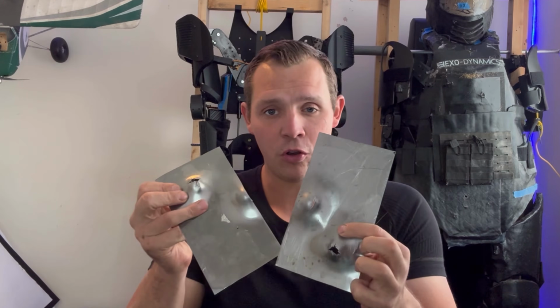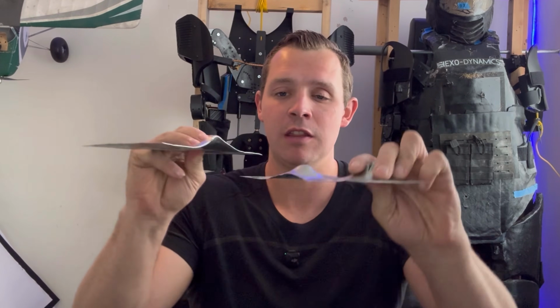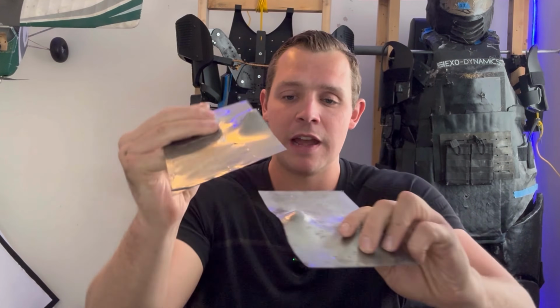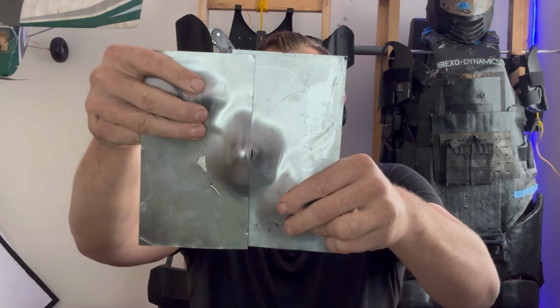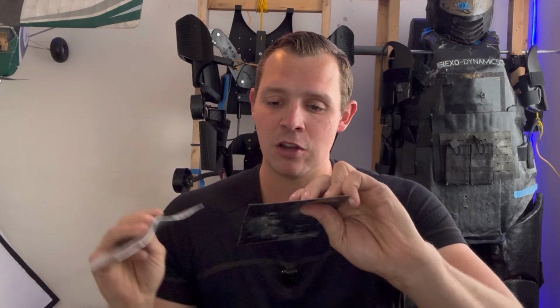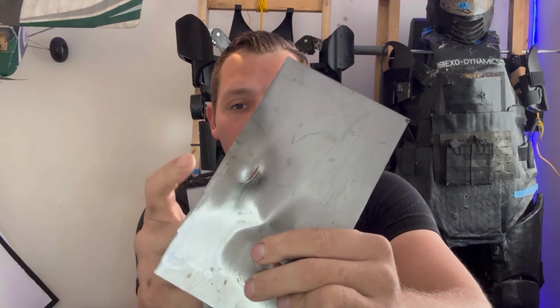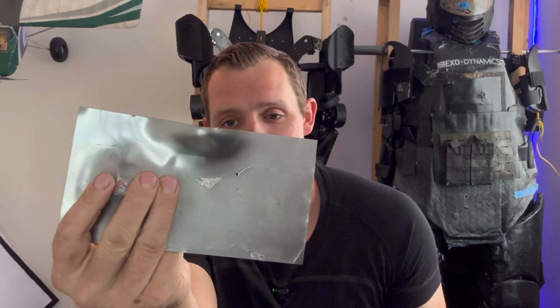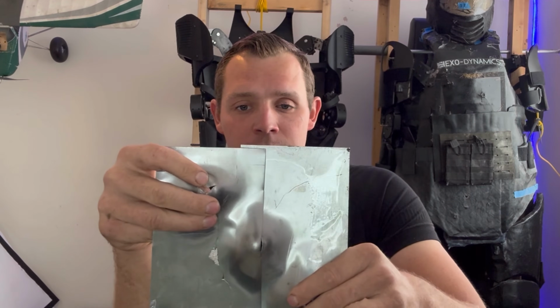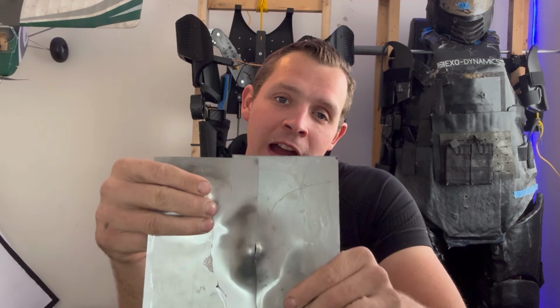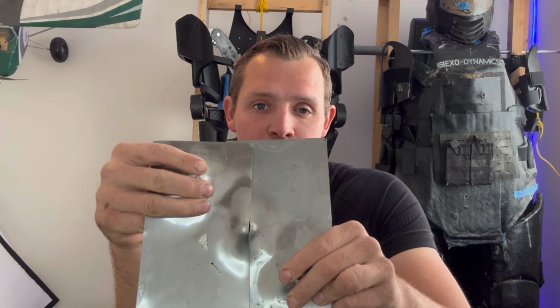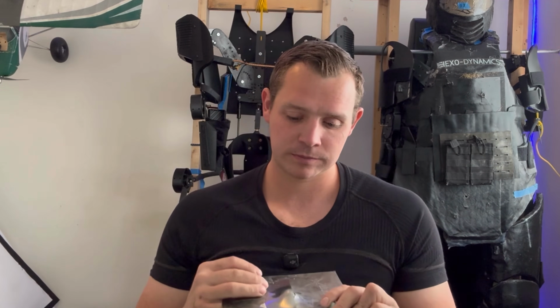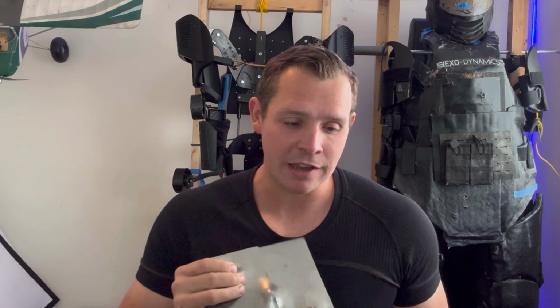But you can see the 2 pieces here. The other holes will make sense soon, but you can see the bulge in the center, and that's where that round hit, like so. And you can see it did stop it. It did just start to pull and fracture the bottom plate, but then the top plate stayed intact. So that would have actually stopped that round just with the ceramic and these 2 steel plates bonded on. And that bonding becomes key later on.